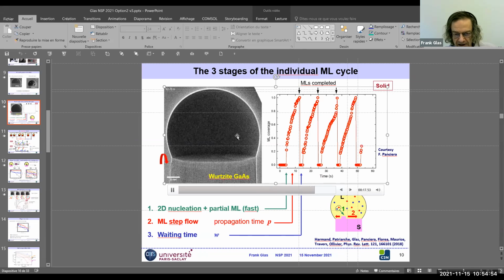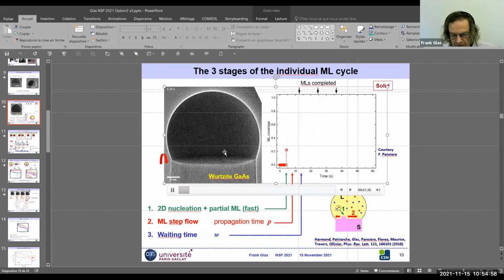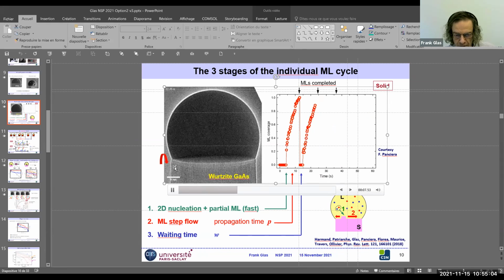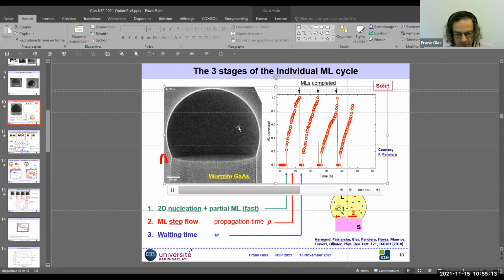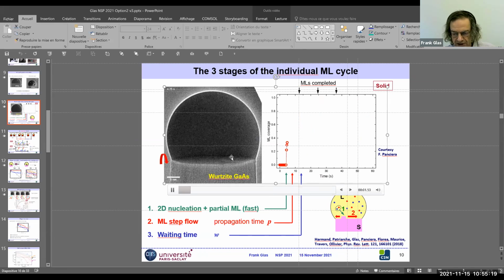So it's very likely that the number of arsenic atoms, say in the droplet, is still not sufficient to grow a full monolayer. The fact that it grows very fast is related to the fact that we can use atoms from the solid to grow the monolayer. So of course, this modifies deeply the nucleation from my point of view, but also the propagation of the monolayer. So the kinetics are very different, and they remain to be studied in detail.